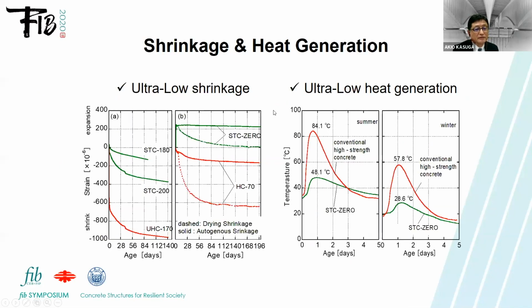And at the same time, this concrete has very good characteristics, ultra low shrinkage. This is the shrinkage of the zero cement concrete and ordinary concrete. The strength is around 70. This is the drying shrinkage, and this is autogenous shrinkage. Compare this type, this type, and this type. The shrinkage is very, very low compared with ordinary concrete.